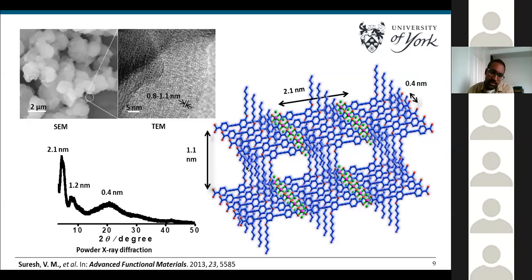So this sort of stacking is evident from the second diffraction peak, where the d-spacing is around 1.2 nanometer, which is matching well with the distance of the 2D coordination sheets. So if we see, the distance between the two dark lines is matching well with this distance. So from this analysis, you can say that the lines in TEM correspond to the pi cores of the 2D coordination sheets.